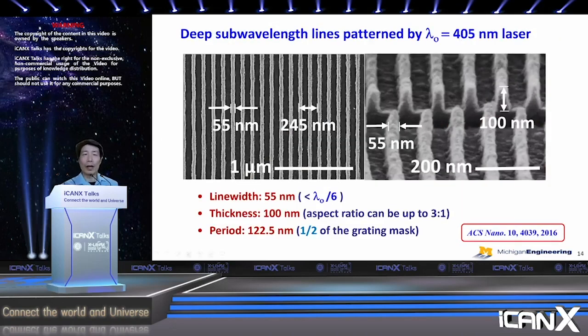But we are able to pattern 55 nanometer feature size with a very decent aspect ratio, 2:1. And we are able to actually get a 3:1 aspect ratio. With such an aspect ratio, you can use this to pattern it, transfer the pattern into another layer, and so on and so forth.